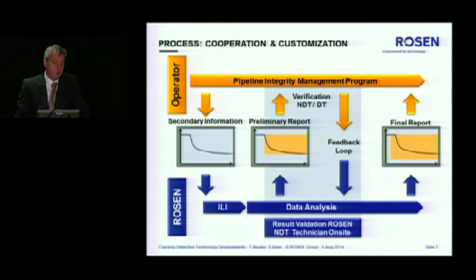Now if we look at the service itself, I found it interesting that in the morning there were a lot of discussions which can actually be found in this picture as well. On the bottom you see our service. We are providing the ILI run, doing the data analysis, providing the reports. But there is a close interaction and communication with the customer required. The operator, the customer, has a pipeline integrity management program in place, and the service delivered by the EMAT technology needs to fit into this program. So there is an exchange of information, and as Brian mentioned, we appreciate getting pipeline properties in advance, because this also allows us to determine the size of a critical defect, taking the tolerances of the tool and so on into account. And then, during the verification of the run, we have close communication with the operator, staying in touch with him, having people on site.